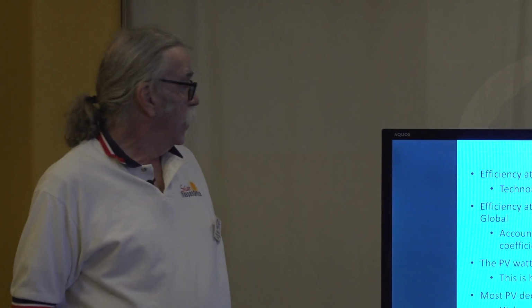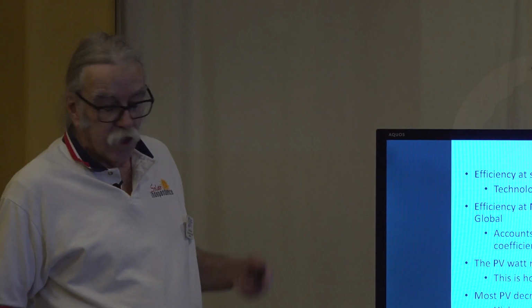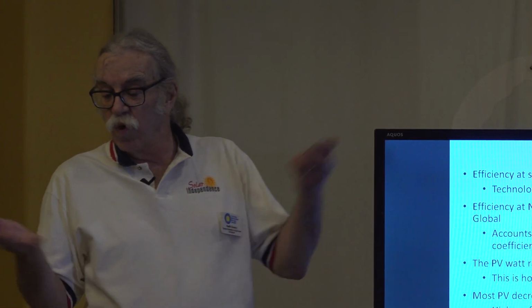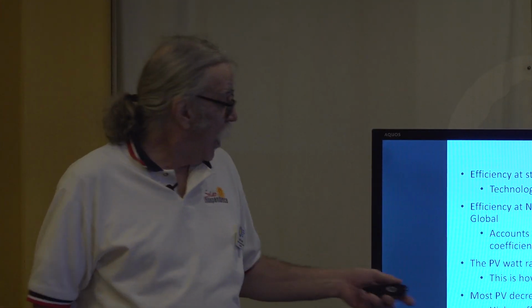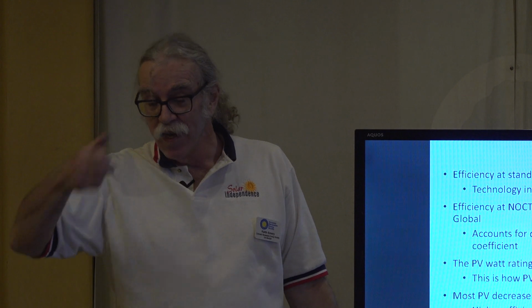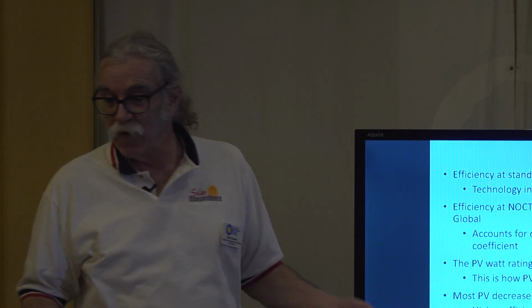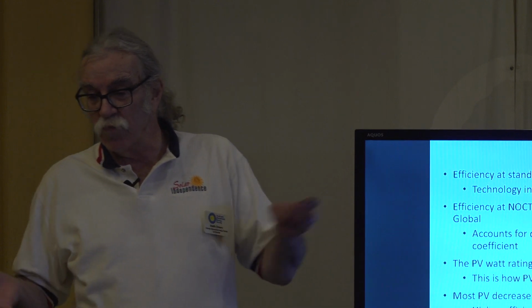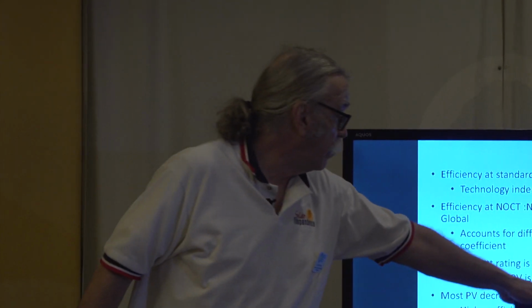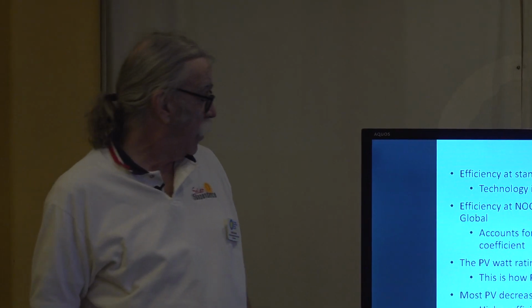Yeah, with silicon, lowering the temperature coefficients will raise the energy. Right now, some PV has 1% per degree centigrade. You rate at 25 degrees centigrade, they get a big boost, meaning their performance looks good, but their energy's crap. Why? Because as soon as you get into any kind of warm climate, or where it's mostly operating, you're losing all your power because of that 1% per degree C.